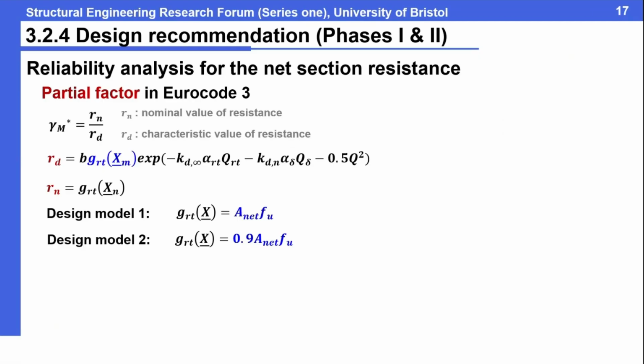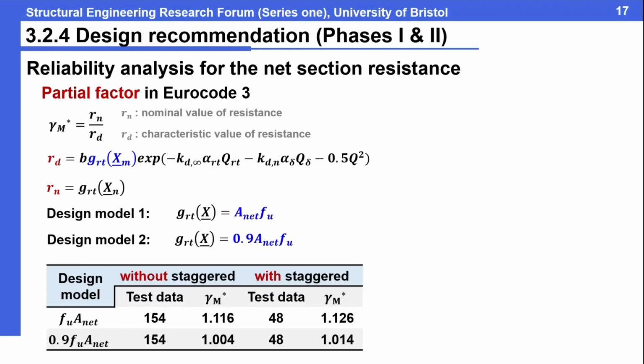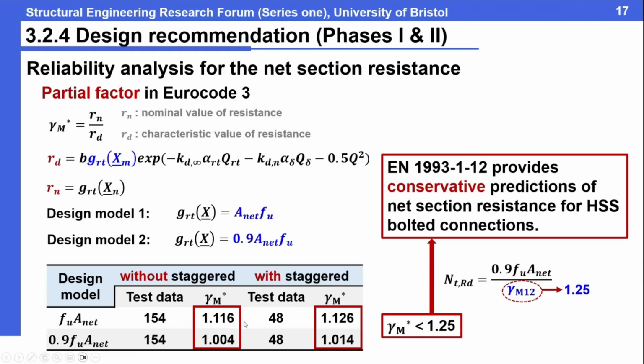So then, based on phase 1 and 2, we conduct the design method evaluation. We mainly conduct the reliability analysis for the net section resistance, staggered or non-staggered, following Eurocode EN 1990. Here we find that the calculated partial factor is always lower than 1.25, and 1.25 is the suggested value from the design code. So it means it's conservative. We can use the current one. It's okay to just use that 1.25.